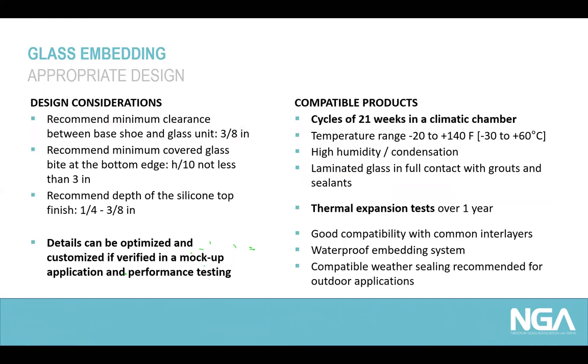We recommend a minimum glass bite in the bottom edge of 10% of the height of the glass unit, but not less than 3 inches. And we recommend a depth of the silicone top joint finish of 1/4 to 3/8 of an inch. Of course, those details can be optimized, but then we really recommend that every optimized and customized solution for those systems is verified in a mock-up application and in performance testing in advance.